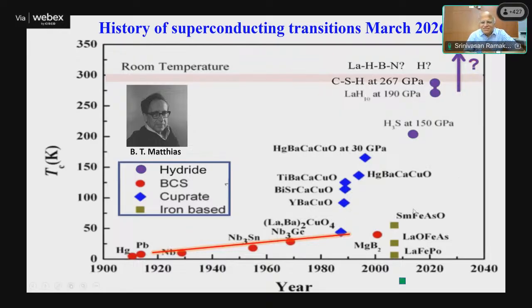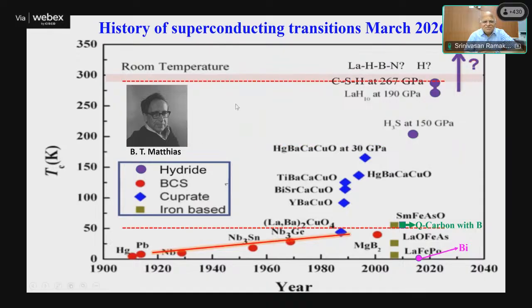And so this research is going on, but at the same time, quietly, there are these quenched carbon-boron compounds. You can add maybe 30, 35% of boron to this amorphous carbon, then you can reach 55 Kelvin at ambient pressure. Though it's not as high as the hydrides, there is interesting physics, and it is good to look at it because it is at ambient pressure. So this is the history of superconductors. And of course, this is the discovery of bismuth, which I mentioned to you. So room temperature is somewhere here. The race is on to squeeze hydrides to higher and higher pressures to reach room temperature superconductivity.